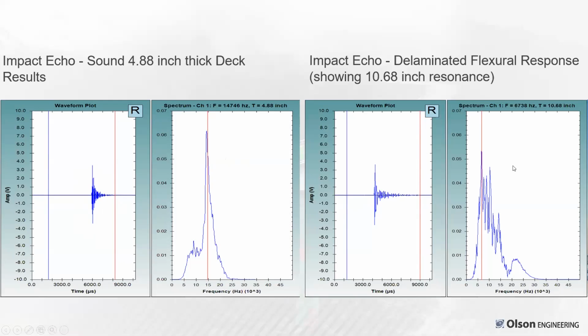Here is an echo that's showing a response at almost 11 inches. On a 5-inch deck, that tells us that this has a shallow delamination near the top surface. So this is an area where you have cracking that's parallel to the surface, just a couple inches down, or an inch or so down.